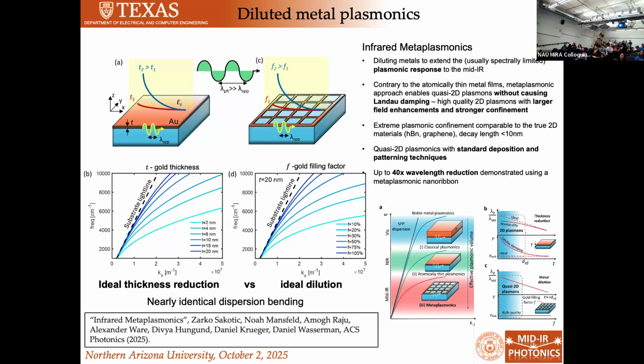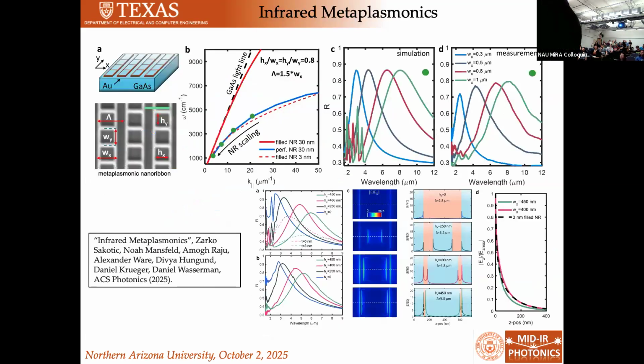So what this actually does is we can engineer this in such a way that every dimension is larger than the Landau damping length, right? It allows us to even go to longer wavelengths with what we are calling the metaplasmonics approach, and we don't get hit with those loss penalties, right? And so we looked at, for instance, could we make resonators out of these metaplasmonic films? And you can see, in fact, if you look at the experimental dispersion of these resonators, they behave a lot like a 3 nanometer thick metal film, except our film is 30 nanometers thick and it's perforated, right? And in fact, if you look at our experiment and our simulation, you see that we get these nice nano antenna responses.